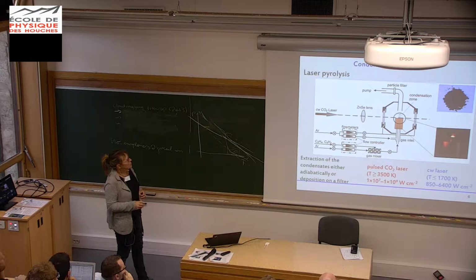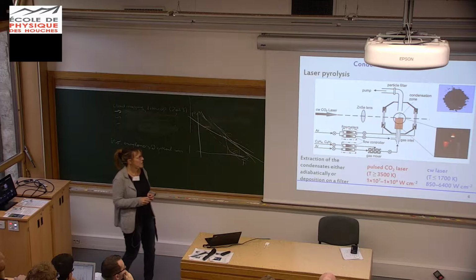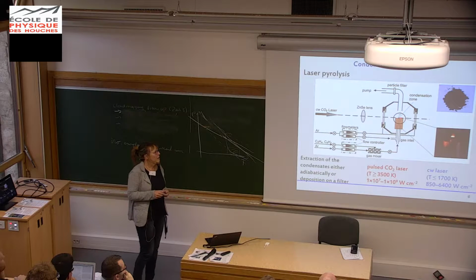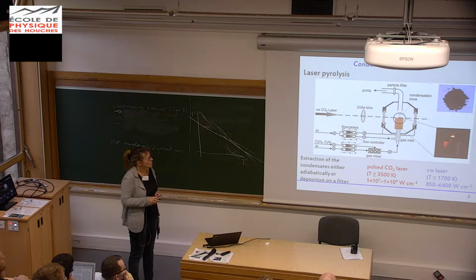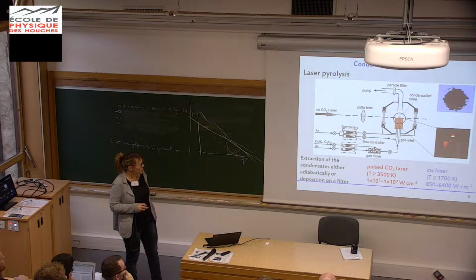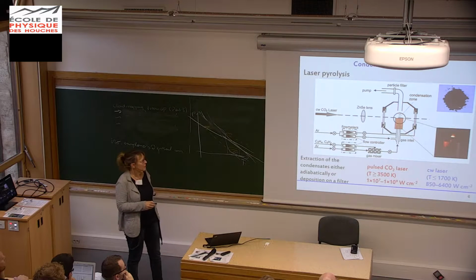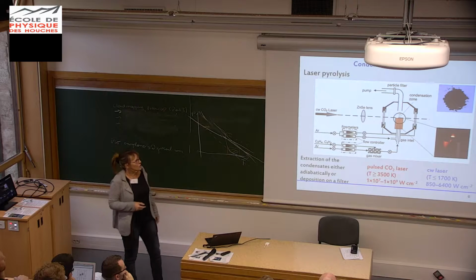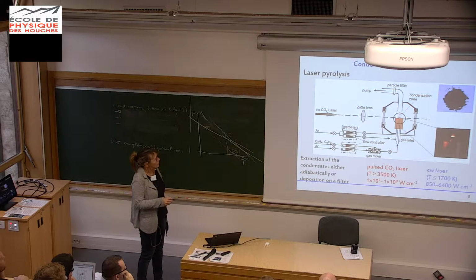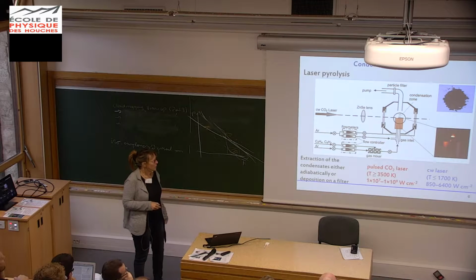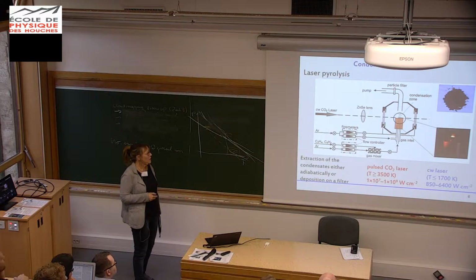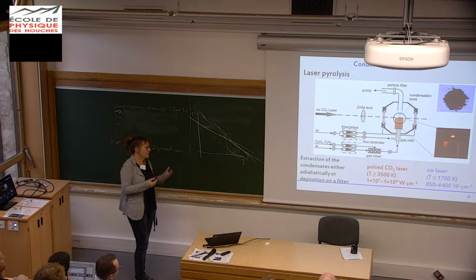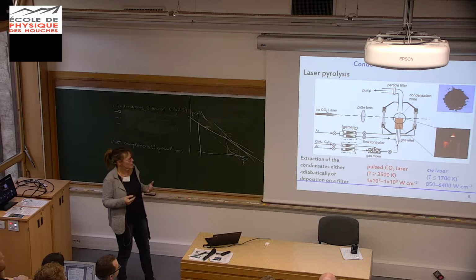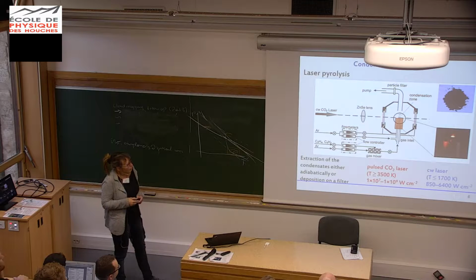Perpendicular to the beam of the gas, we have a CO2 laser which dissociates the gas. Due to collisions with the quenching gas, we get supersaturation in this zone and homogeneously condensed particles. We can finally deposit the particles on a filter, or extract them very efficiently by adiabatic processes like adiabatic extraction through a nozzle and a skimmer.